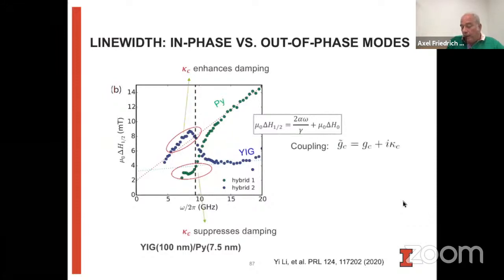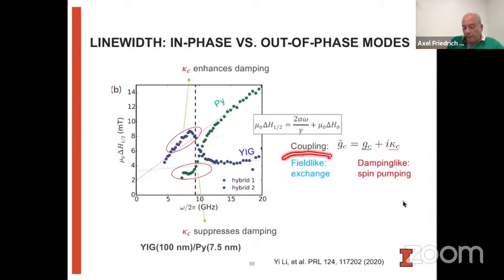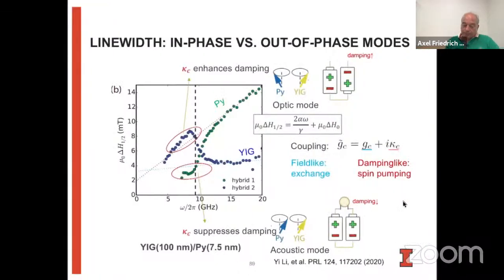And so we can express this by using a complex coupling constant, which has a real and an imaginary part. The imaginary part is this dissipative coupling. By analyzing it further, we can see that the ordinary coupling is a field-like coupling that comes from the interfacial exchange coupling. But this dissipative, damping-like coupling comes from spin pumping between these two magnetization modes. And we see that for this hybrid mode, the dissipative coupling increases the damping, and here it actually suppresses the damping.